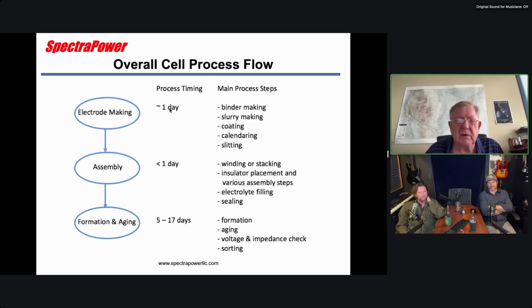So electrode making takes, as a very round number, about a day. You have to make the binder that holds the electrodes together. It's basically a plastic binder. Then you have to make a slurry. You have to coat it, and then you have to compress it with a roll press, a calender, and then you have to slit it to the size you want. Cell assembly, think of that as another day. So you wind or stack, like we talked about. You have an insulator you have to put down in the cell. You have to fill it with electrolyte, and you have to seal it. And then formation and aging can take 1 to 2 weeks.